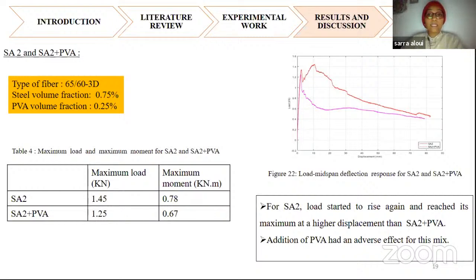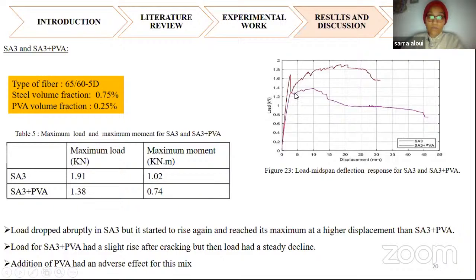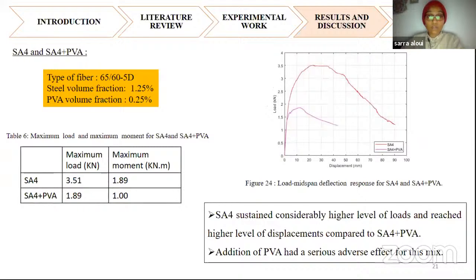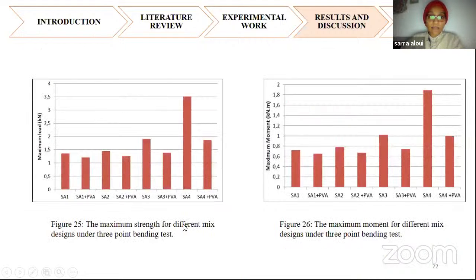For the third one, we can also see that the specimen with PVA has a lower maximum load. We can say that the addition of PVA has an adverse effect for this mix. The fourth one, SA4, has a higher content of steel fibers. We can see here the big difference between the maximum load and the maximum moment of the two specimens. Here we can say that the addition of PVA has a serious adverse effect for this mix. From this graph, we can see that SA4, the last specimen, has the highest maximum load and maximum moment compared to the other specimens.